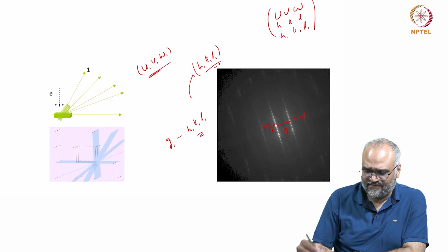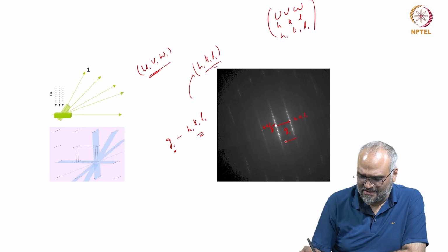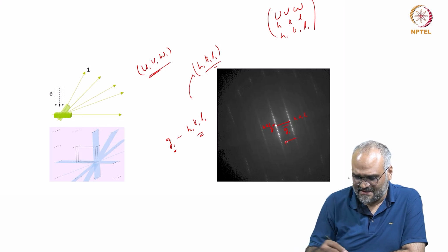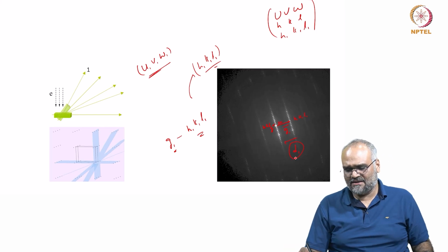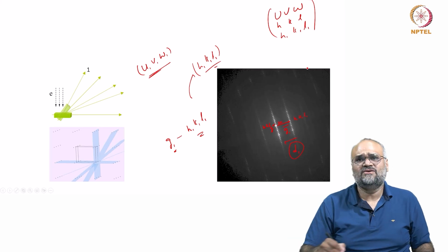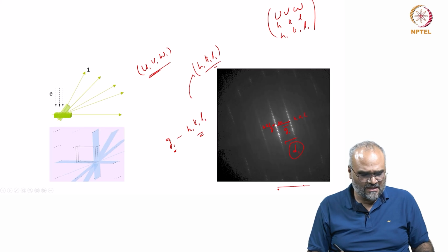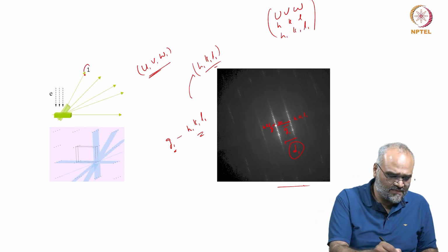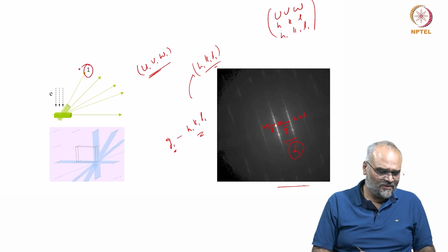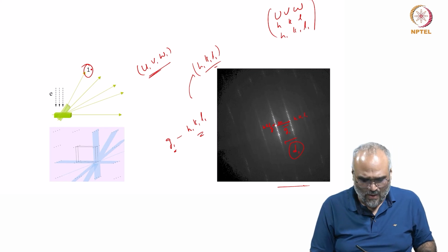Now, let us say the value that I determine, if G1 is the vector, has a modulus of say value D1, and this D1 and D together can be used to reconstruct the entire two-dimensional reciprocal lattice that I have in this particular projection. This is, let us say, from the first orientation, which is written as reflection 1 or diffraction pattern 1.